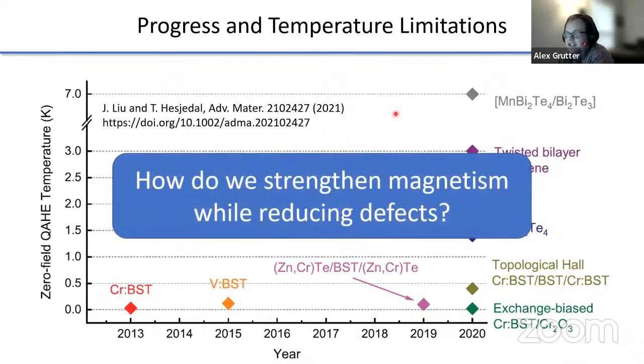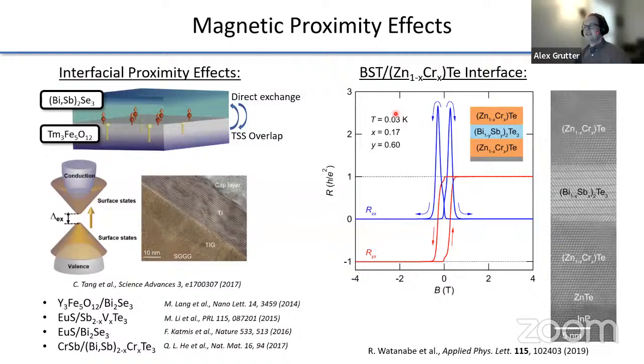So the question becomes, how do we strengthen magnetism in these systems and get something more uniform while reducing the defects? And here it's useful to start thinking about magnetic proximity effects. All we really are interested in is getting the surface of your topological insulators, like bismuth selenide, bismuth antimony telluride, to magnetize. We really just need to induce a gap in the surface state. And one of the ways we might do that is by taking a really nice uniform magnetic material and growing